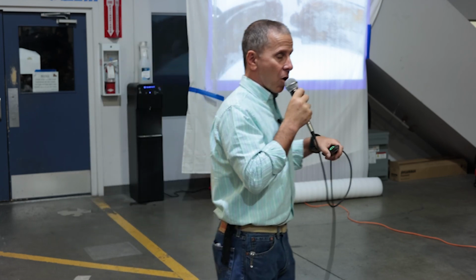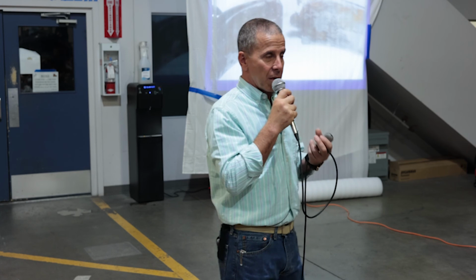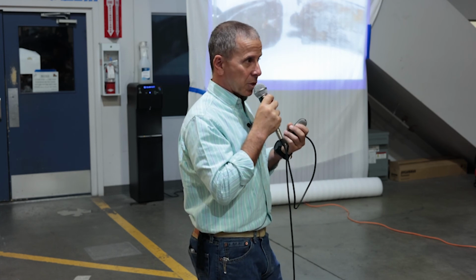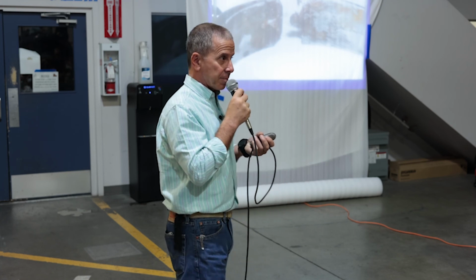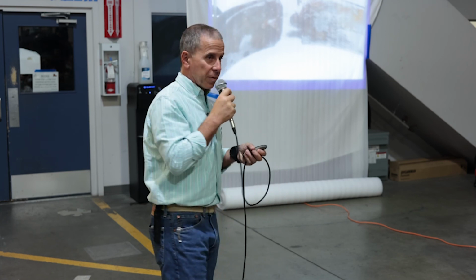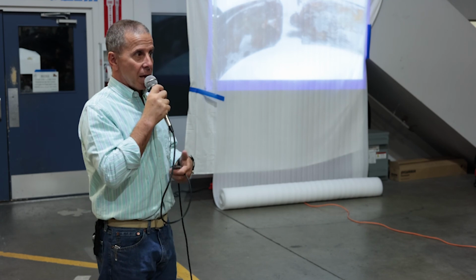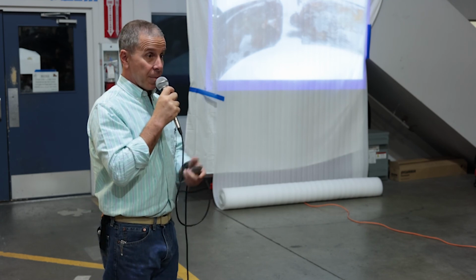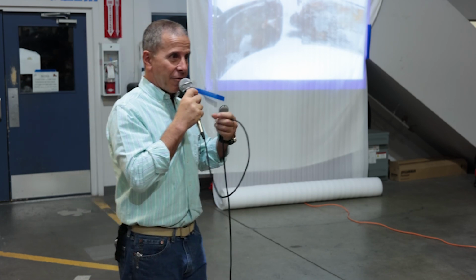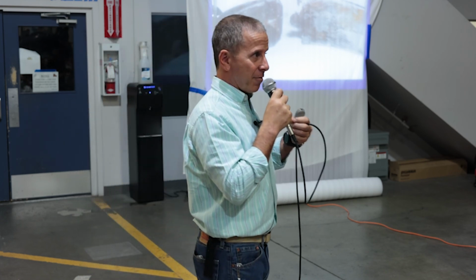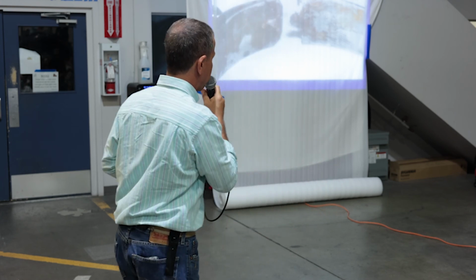How can you prevent this on a T-bolt clamp? There are some T-bolt clamps that use an interlocking feature rather than a spot weld, and they tend to be less susceptible to this. Alternatively, before the T-bolt clamp is installed, it can be saturated with a corrosion inhibitor like CRC heavy-duty corrosion inhibitor, that penetrates into that fold and fills that void with the corrosion inhibitor, keeping the water out. That's been my approach to that.